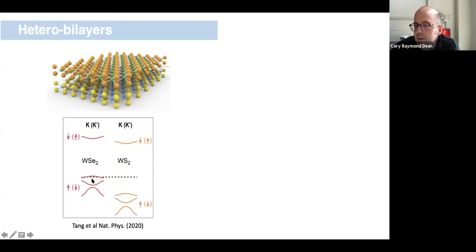We still get a creation of a flat band in the system because there's a Moiré potential that develops, and that Moiré potential induces a flat band at the top of the valence band of one of the layers. But because the other layer has an energy offset, there's no hybridization between the layers. So we really have a very pure system now. We have basically a single valley state of one of these layers. Okay.